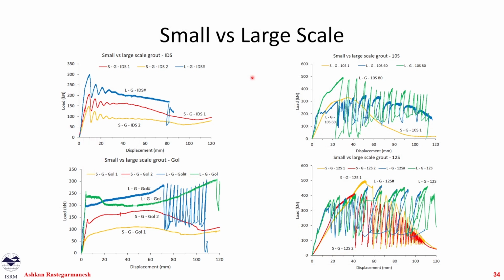The difference between our larger scale and smaller scale tests, if we put these two together, we realize that in our smaller scale tests, for example in this Gol test, our repeatability is less. So we did two tests, but we got everywhere between like 50 kilonewton to 150, compared to the larger scale where the values are bunched together. This 60 and 80 that you see are basically the torque that we put on the external confinement bolts, if you remember from the larger scale section.